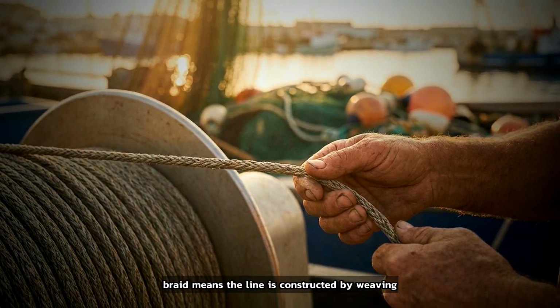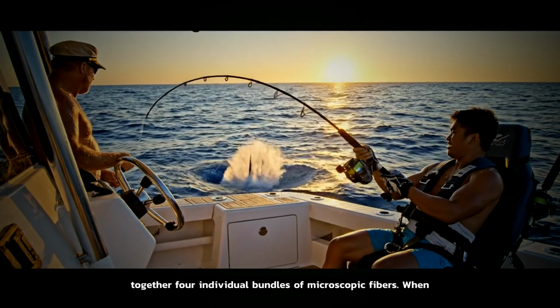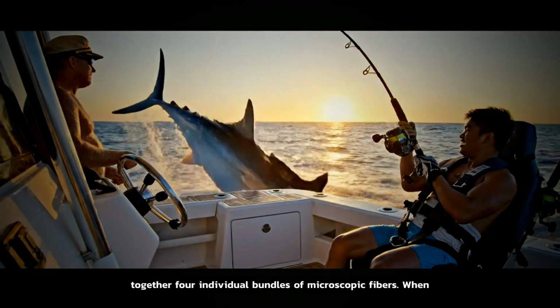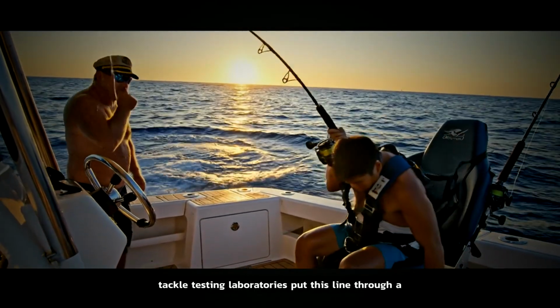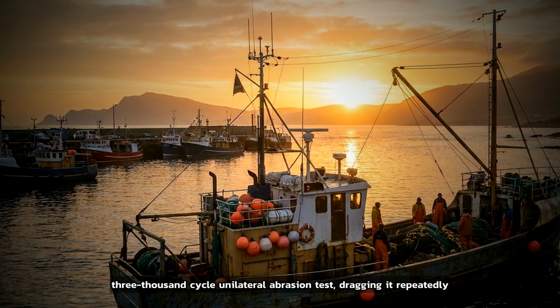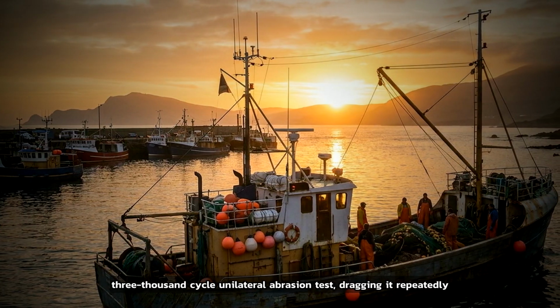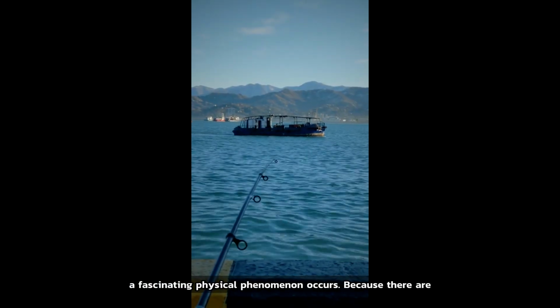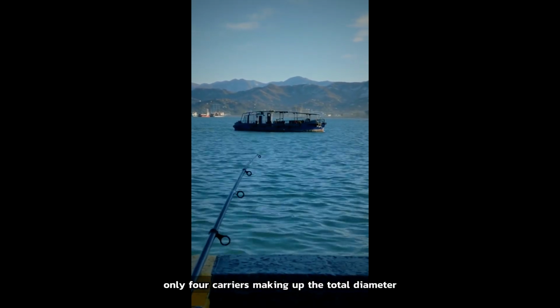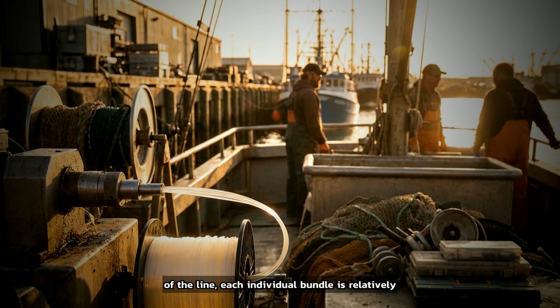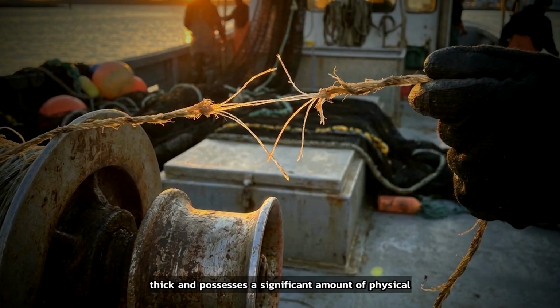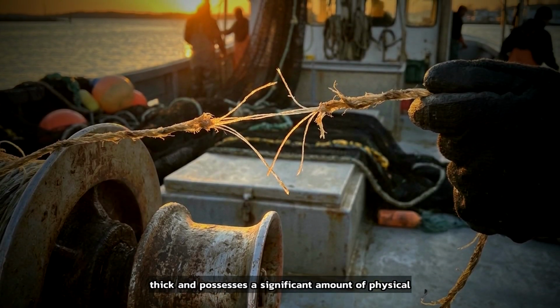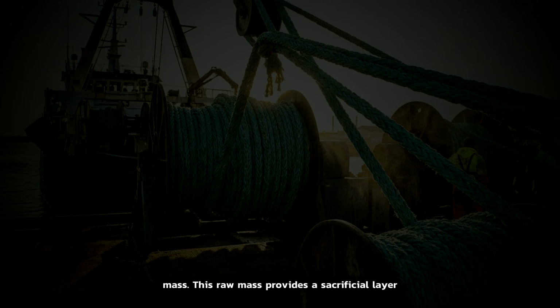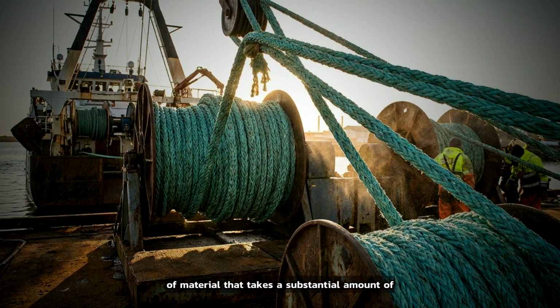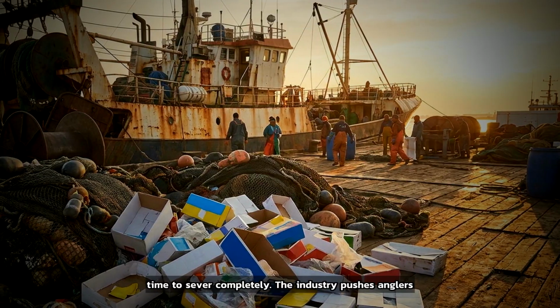A 4-carrier braid means the line is constructed by weaving together 4 individual bundles of microscopic fibers. When tackle testing laboratories put this line through a 3,000-cycle unilateral abrasion test, dragging it repeatedly across a rough ceramic guide under heavy tension, a fascinating physical phenomenon occurs. Because there are only 4 carriers making up the total diameter of the line, each individual bundle is relatively thick and possesses a significant amount of physical mass. This raw mass provides a sacrificial layer of material that takes a substantial amount of time to sever completely.